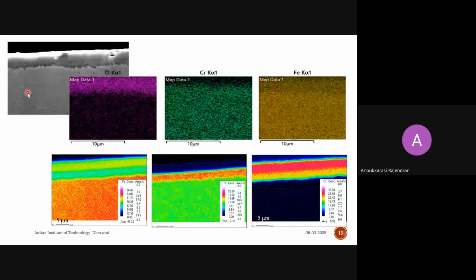So this is the corroded layer of a steel sample. For the same sample and same region, we have done EDS mapping as well as WDS mapping. This is for the oxygen concentration. You can see the brightness shows the presence of oxygen at the top and the dark region showing the depletion of oxygen. In the same way for chromium, this is the whole thickness of this layer. If you see, chromium is depleted only in half of this layer and in the rest there is a presence of chromium. For iron, it is partially dull here, and there is enrichment here. So this is the base material. I can see the enrichment of iron here, partially diffused here. It is iron oxide, so partially iron you can see here. Again, chromium from the sample is little diffused here.